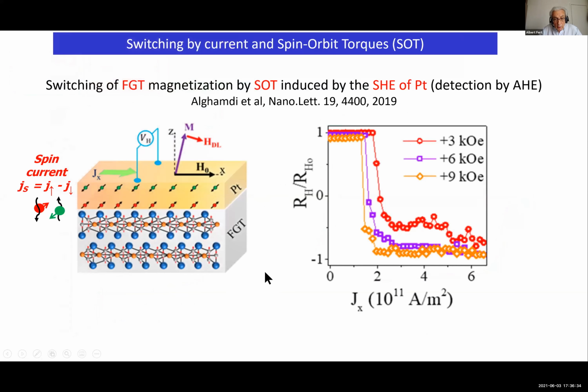Going on with this sort of spintronic properties, switching by current and spin orbit torques. So I said already that the spin orbit effects are large in this compound because spin orbit is a condition for escaping from the Mermin-Wagner theorem. So for example, a typical example of switching of FGT, of this 2D magnet FGT, by the spin orbit current, the spin current generated by spin Hall effect in this layer of platinum.